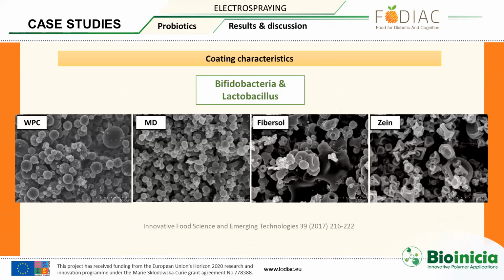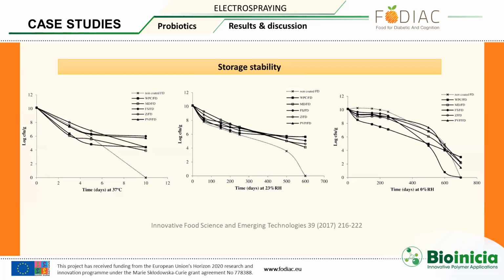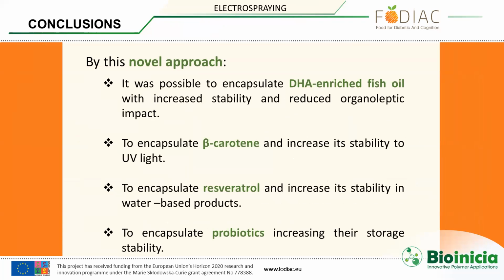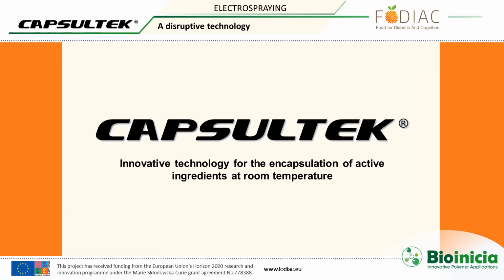Another approach that we have taken for the encapsulation of probiotics is to coat the probiotics with a layer of particles, in this case whey protein, maltodextrin, Fibersol, which is a kind of maltodextrin, and zein. This was like a sandwich. And even in this case, we observed that the sandwich provides a higher stability than the freeze-dried non-coated bacteria. So by this technology, we can encapsulate omega-3 oils, beta-carotene, resveratrol, and also probiotics, and increase their stability. However, the disadvantage of this electrospraying technology for encapsulation is the low throughput.